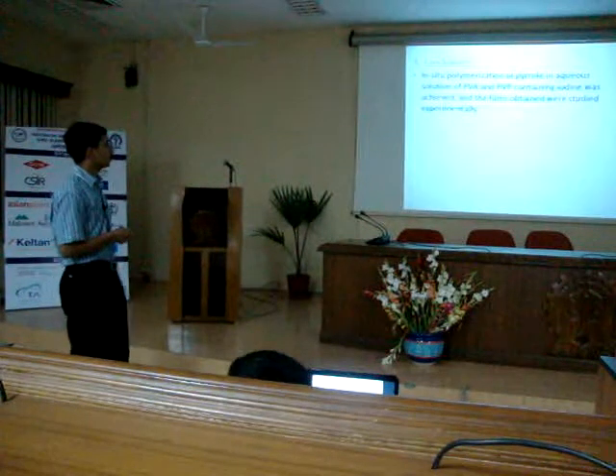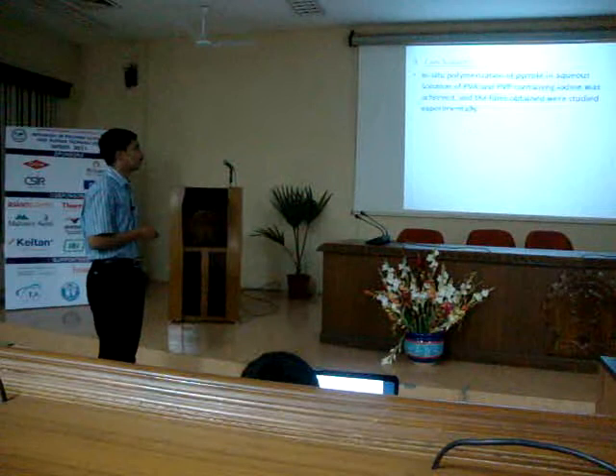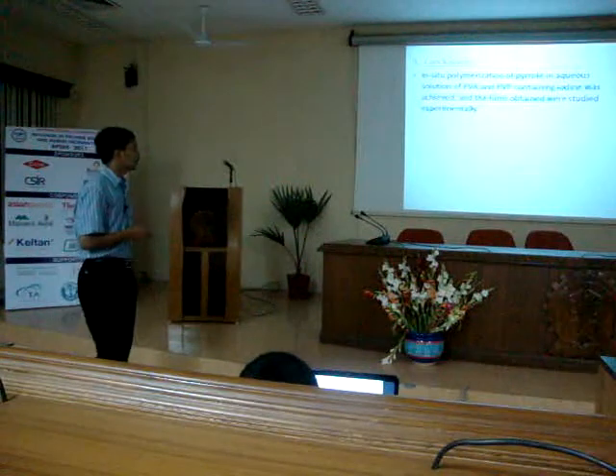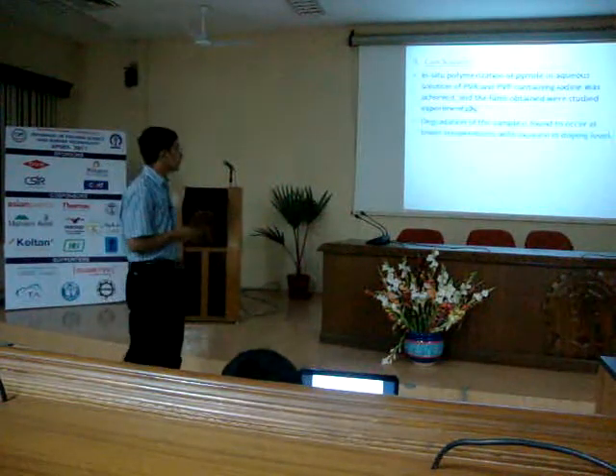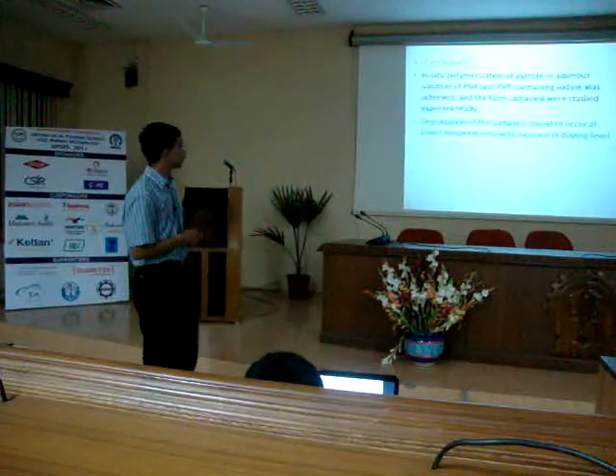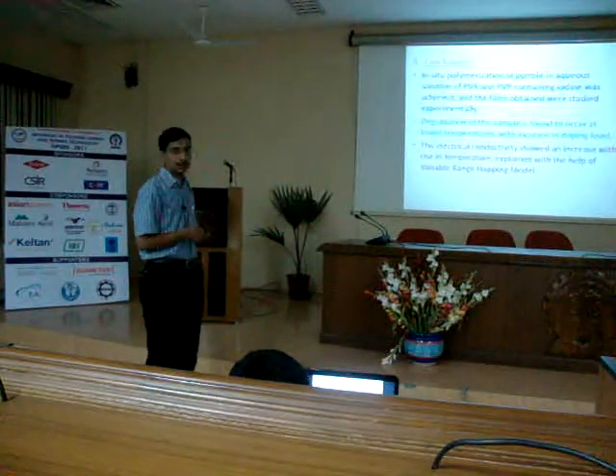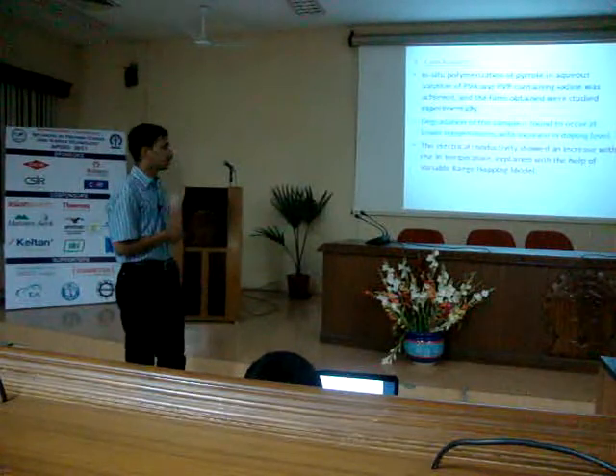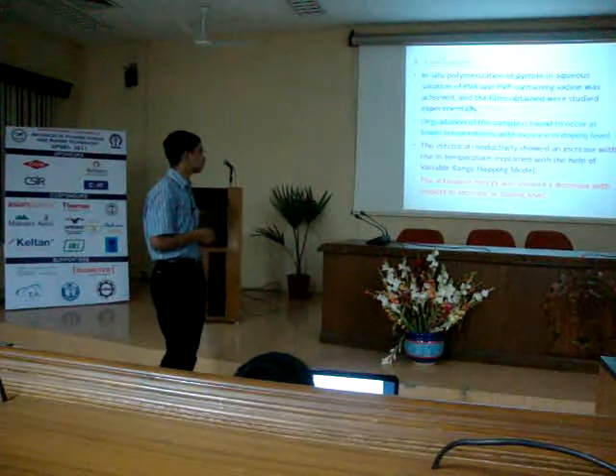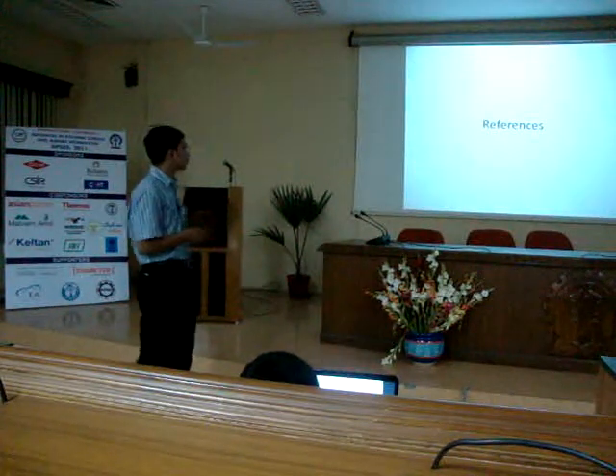Conclusions: in situ polymerization of pyrrole in aqueous solution of PVA and PVP containing iodine was achieved and the films obtained were studied experimentally. Degradation of the sample is found to occur at lower temperatures with increase in doping levels. The electrical conductivity showed an increase with rise in temperature, explained with the help of variable range hopping model. The activation energy showed a decrease with increase in doping level. References, these are the references. Next slide.